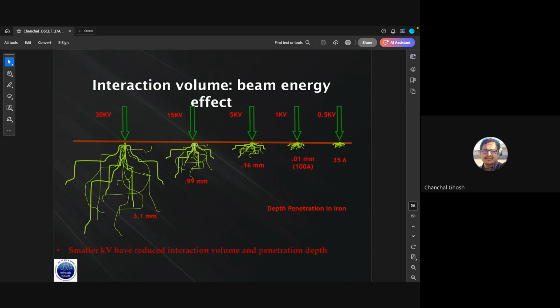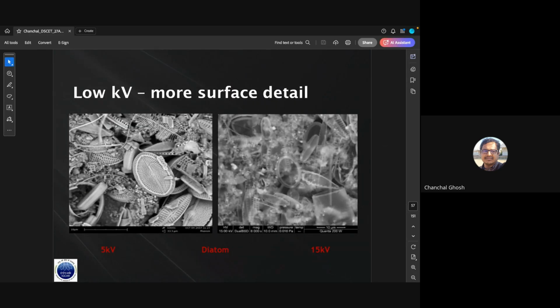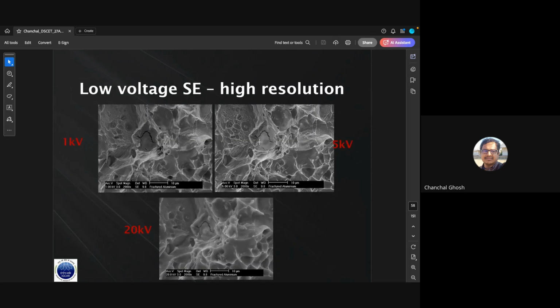So from here, you can see that if you want to go for very high resolution, then you want to go for the lower kV, so that the interaction volume becomes lower and lower. This is again one example. This is a biological sample. This image has been grabbed at 5 kV and this image has been grabbed at 15 kV. Here you can see the 5 kV image is much clearer and the resolution is much better than the image grabbed at 15 kV.